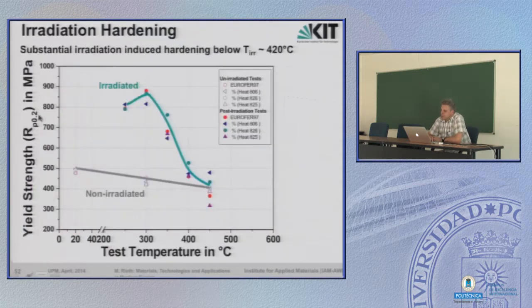That's the summary. Test temperature and yield strength. In the non-irradiated material, yield strength decreases with growing temperature, and the other way around, if we irradiate, in this case 9% chromium steels, at 450°C, there is almost no hardening effect, but if the temperature goes down, then hardening goes up in a rather impressive way. Starting from 400 MPa, we end up at more than 800 MPa after irradiation of 16 dpa.